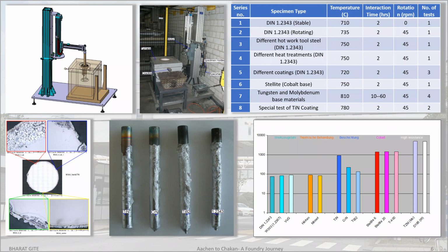This whole methodology has given BMW the opportunity to develop a much more systematic approach of quantitative and qualitative investigation of the influence of molten aluminum on different materials and coatings. I'm proud to mention here that to this day, BMW is using the titanium nitride coating solution, which resulted in enhancing the sprue life from 80 to 500.